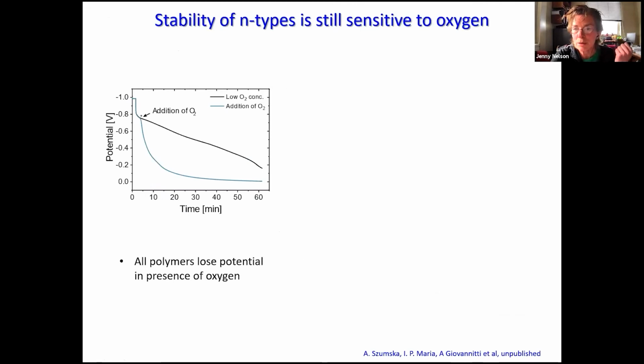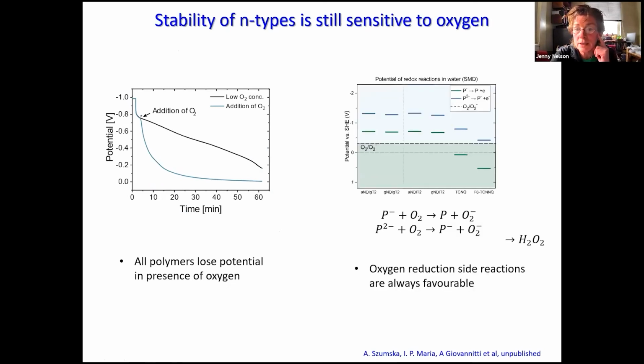And when we work in the presence of oxygen, we still find that our polymers lose potential in the presence of oxygen. And this can be related to the reduction potential of the polymer. All of the reduced polymers in the polaron or bipolaron state are thermodynamically capable of reducing oxygen and leading to an oxygen reduction side reaction, which we think is going on. We're pretty sure it's going on because we find peroxide in the solution when we work in the presence of oxygen. So that's a problem that still has to be solved.